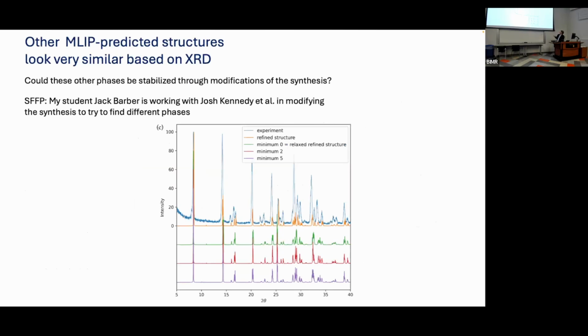Experimentally, this is the difference. For the ones within the 5th ground state, I'm showing the XRD that we could generate computationally based on the structure that we predicted. And this is compared to the experiments. What's interesting to us is that the XRD spectra overlap, even though the organic bit is a little bit different in each case. That's because the XRD is largely based off the inorganic lattice, which gives the largest signal. And there are very subtle differences between these spectra. So it's good that the experimentalists can reproduce our prediction. That's a validation of our method.